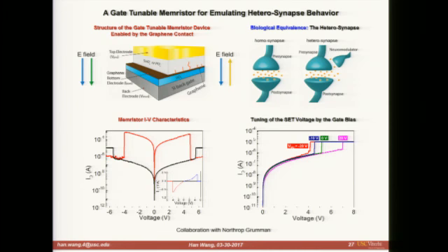And if the gate field opposes the bias field, it's going to suppress this filament formation process. If the gate field is much larger and also opposes the bias field, it will dominate over the bias field, and you can get inhibitory responses.